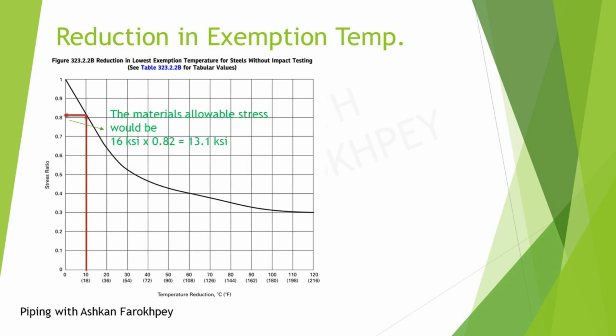Some guys also look at this table from another perspective. They say when doing a stress analysis in Caesar II, and when one of the temperature cases is colder than the limited temperature in Table A-1 for each material, Caesar II itself multiplies the material's allowable stress by the stress ratio, and the amount of the stress ratio is obtained reversely from this figure. To be more clear, assume that the stress man is modeling an A53 Grade A material with 16 ksi allowable stress at ambient temperature, and let's assume that one of the temperature cases is 2 degrees Fahrenheit. This means that the guy is using the material 18 degrees Fahrenheit below the minimum temperature specified in Table A-1, so his material doesn't have that 16 ksi allowable stress anymore.